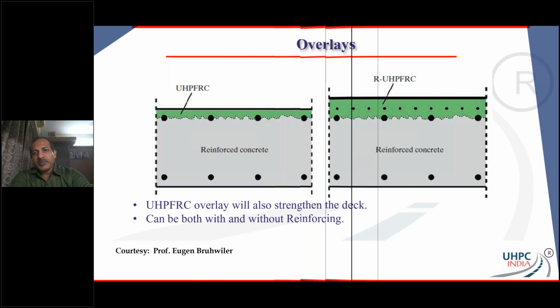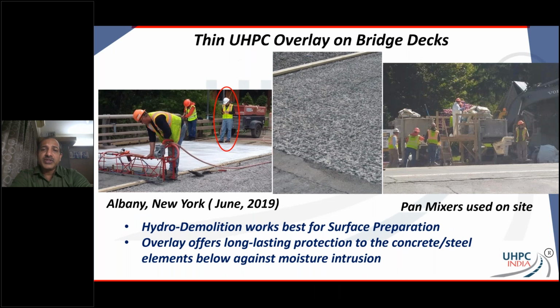Quick picture in the middle, I want to show you the middle first. A very, very good surface treatment which was done, or surface preparation. Hydrodemolition was used. On the left hand side, you see simple screed vibrator that was used to screed up the UHPC. And of course, immediately afterwards, a curing compound was put over it. On the right hand side, what you see are pan mixers, and UHPC was brought in jumbo bags or bulk bags and just dumped into the pan mixers. Then they put ice, they mixed it. Once the mix was done, they put the fibers, mixed it again, and then they poured the UHPC.